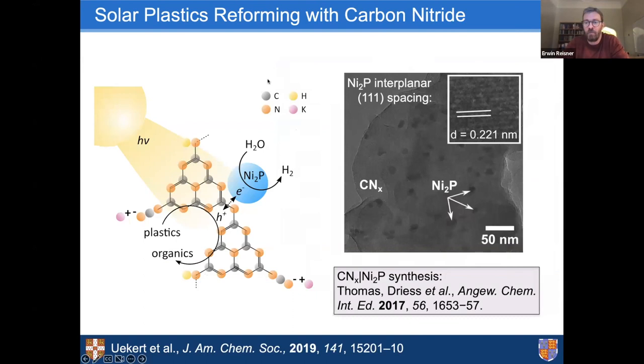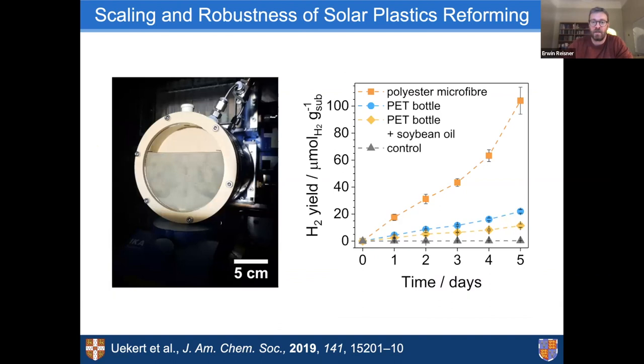Also here we have moved on. So instead of cadmium sulfide, we can also use carbon nitride polymer photocatalysts. In this case, we replaced the molecular nickel catalyst with a nickel phosphide hydrogen evolution catalyst. This can just be deposited on the carbon nitride. So we have an integrated light absorber with a co-catalyst. And also here, when we photo-excite the carbon nitride, we extract the charge from the plastics and generate the electrons for hydrogen generation.